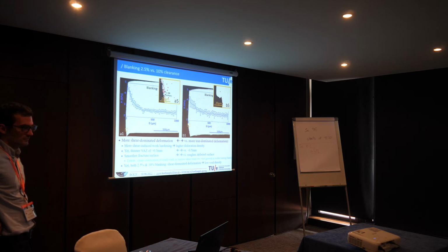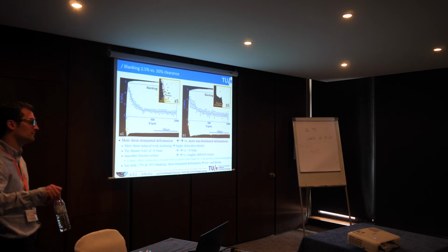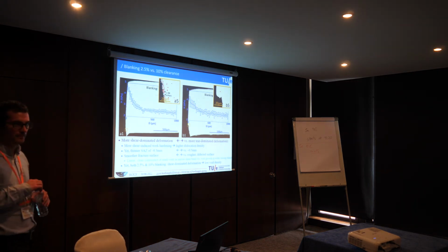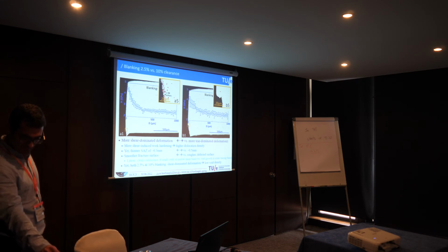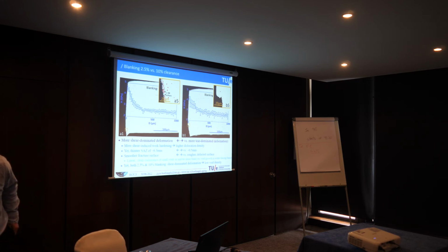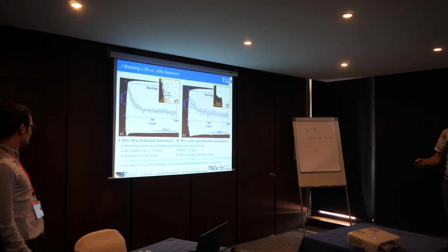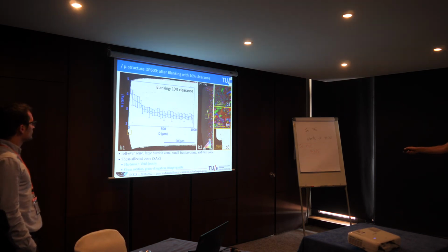Yeah, so the very clean dislocation walls, typically, if you do some cyclic loading, then the dislocations start rearranging themselves in walls, and internally the EBSD quality is sort of recovered a bit. But if you do a one-time deformation, typically you don't see this immediately, these long-range structures that you get from the dislocation structures. So basically the dislocations are everywhere, and it's just generally decreasing the EBSD quality. That's something we've also seen if you do monotonic loading for steels, and also other metals. So I'm not completely surprised that we see this kind of behavior.